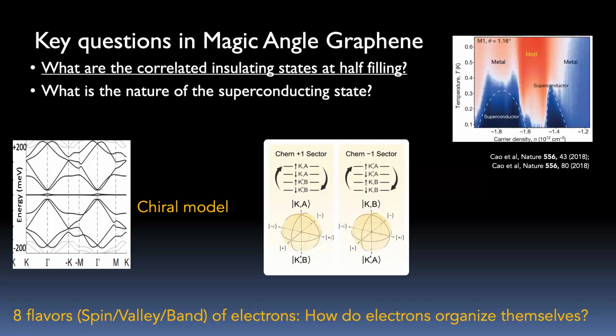You twist these two layers, you get these flat bands, and we can think of them as a conduction and a valence band, which are relatively flat, about 10 or 12 milli-electron volts in width. These bands have positive and negative Chern numbers. When you half fill them, you get an insulating state, which was your discovery, first thought to be a Mott state. I will show you it is not a Mott state. Then when you dope away from the insulating state, you get superconductivity. The nature of this superconductivity and its resemblance to all these different correlated superconductors is a question.